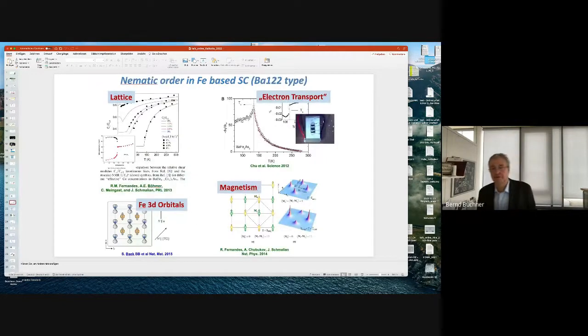So what about the origin? So this is, let's say, my attempt to bring this closer to you. In the first place, we have this phase transition coming from a tetragonal lattice to an orthorhombic lattice. So that means the lattice is involved. And if you measure, for example, the elastic constants, you see a softening of the lattice going ahead. So it's not only this phase transition, but there's some evidence for some lattice fluctuations. So the lattice plays a role.